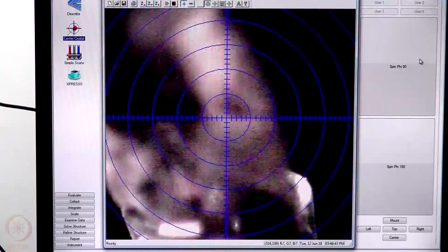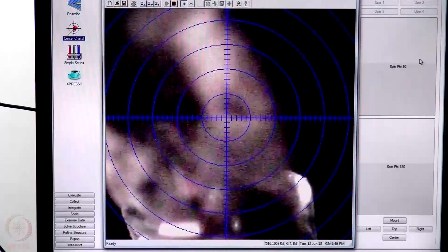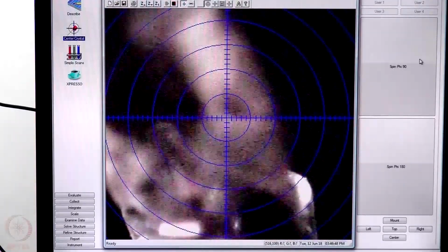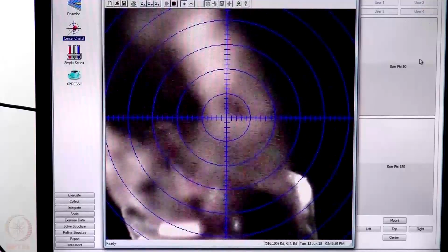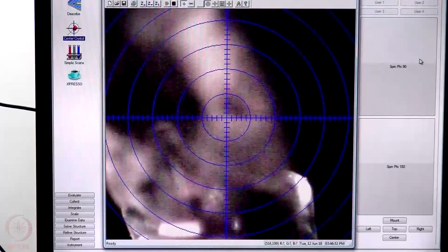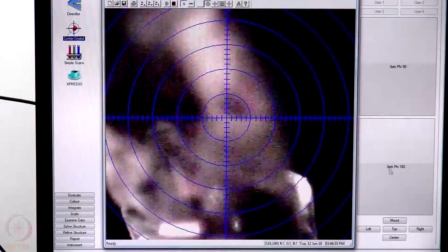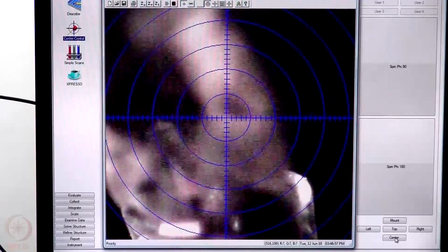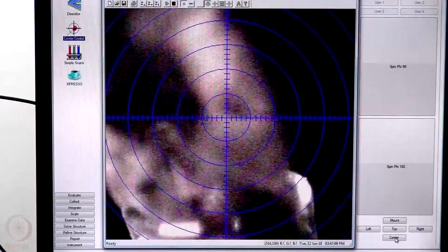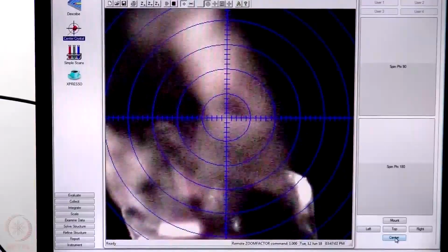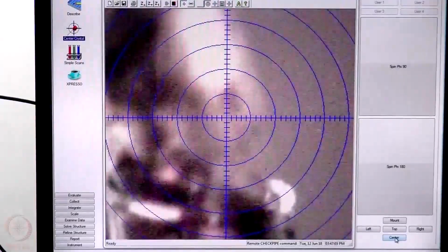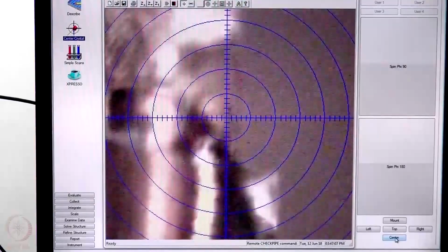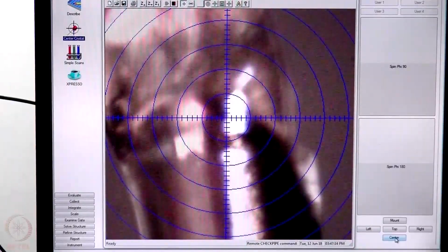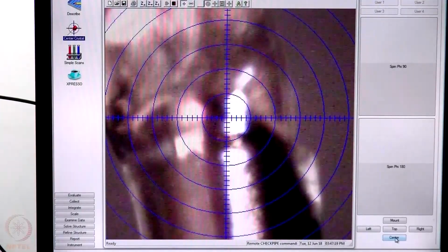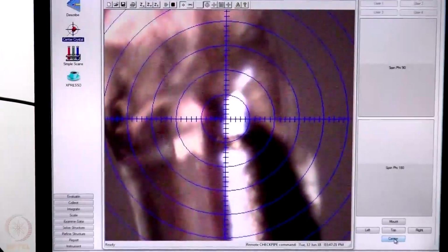So on the screen what we can see is the defocused crystal, which means that the crystal is not centered. So we need to center the crystal in front of the X-ray beam. So from the current position, I would take this crystal to a different orientation, which is called the center orientation. So what we can now see is the crystal is still defocused. What we need now is to align the crystal on the beam.